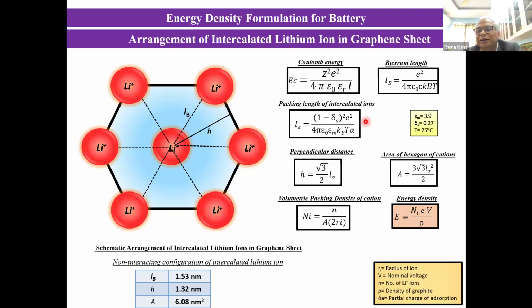So when it is at the Bjerrum length, they are not interacting because thermal energy is available to them. So that will be my equilibrium value for how far these lithium can sit from each other. We have taken a triangular lattice model to estimate that. And then we say, okay, now there is an adsorption energy. What will the length be? Because I know this much is lowering the separation of these things. So you take that same Bjerrum length and divide by the factor that the energy of adsorption is scaled with respect to thermal energy, alpha, which is a number. Then this formula gives you the length lambda.